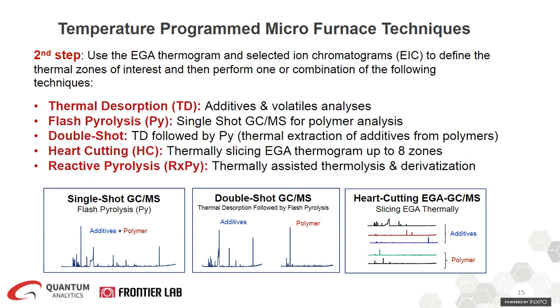So instead of having one chromatogram for single shot for additives and polymer, whenever you perform a double shot analysis, you thermally extract the additives and you obtain two separate GCMS chromatograms. Double shot also, as I mentioned, eliminates the need for any solvent extraction or sample preparation prior to your analysis. One additional note, which we talked about a little bit on the right-hand side about the heart cutting technique: if your EGA contains more than 2 peaks, or if you want to perform reverse engineering and deformulation, you could perform heart cutting EGA, where you thermally slice your EGA thermogram into different temperature zones. And you can perform up to 8 zones on one single sample. So you obtain separate GCMS chromatograms for each zone from your EGA.